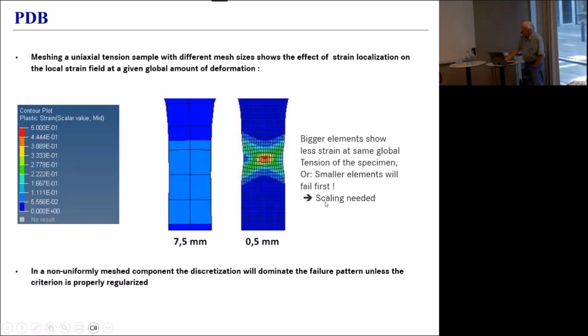So Marian was so kind to do some simulations to make that clear. And you see the principle here when we model a real life tensile test with a very coarse mesh and a somewhat finer mesh of say 0.5 millimeter. And you apply a certain displacement to both models, you see that the strain values that we get in the fine mesh are much, much higher due to the localization. If there would be no necking, it would be the same. But since there is necking, we get strain values that are very different. And for a given strain to failure, the finer mesh will, of course, fail first.